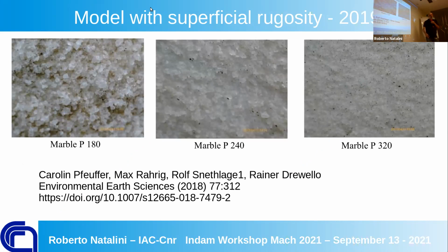And then we want to go forward. What are the other directions that we move? Recently, with Cecilia Cavaterra and Bonetti from Segregazione and Francesco Freddi, we tried to add some feature to this model. For instance, rugosity, because here you see 3 kinds of marbles treated by sandpaper of different granulosities. So you find here 180, 240, 320. And it's completely different, the surface you are observing. And that's from a paper about this kind of study of environmental science. And so you ask, what is the behavior of this surface when you have a different granulosity?